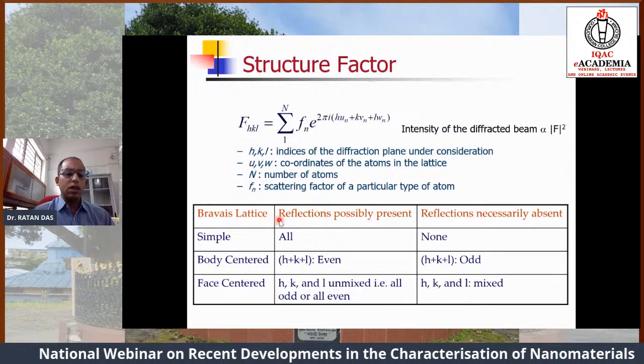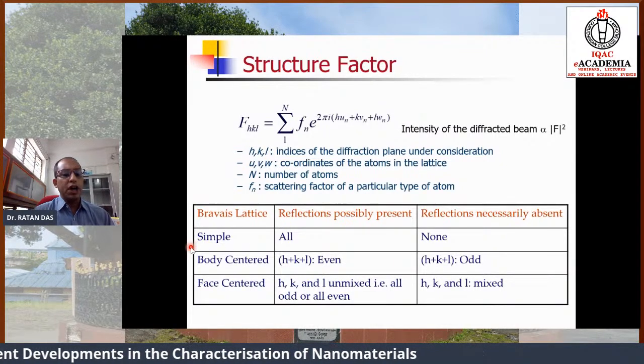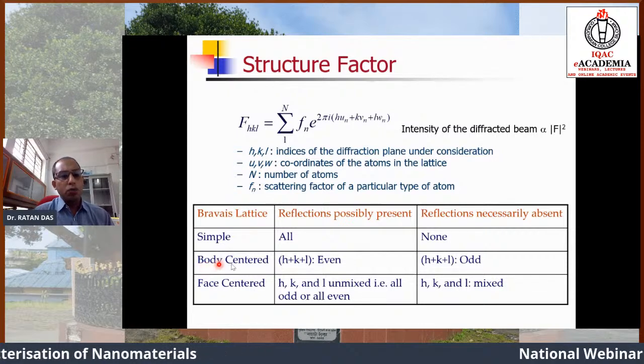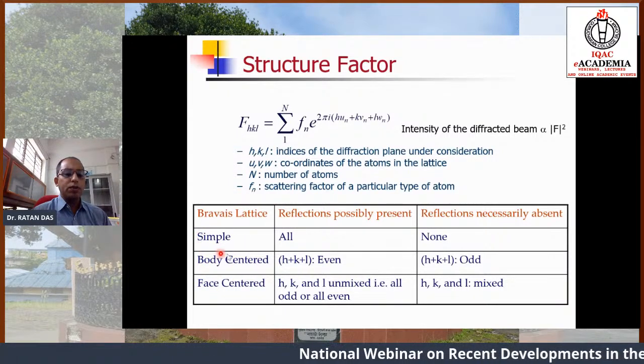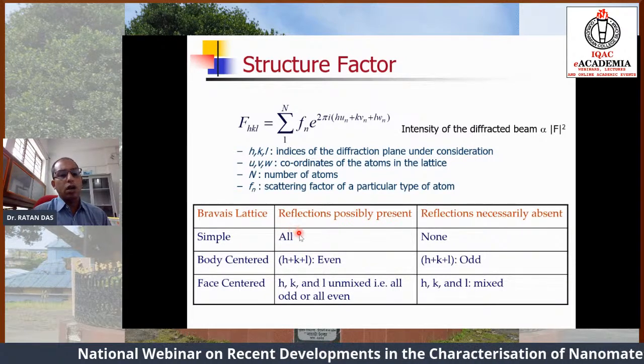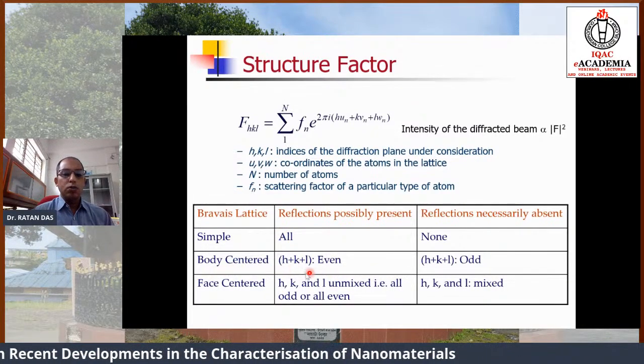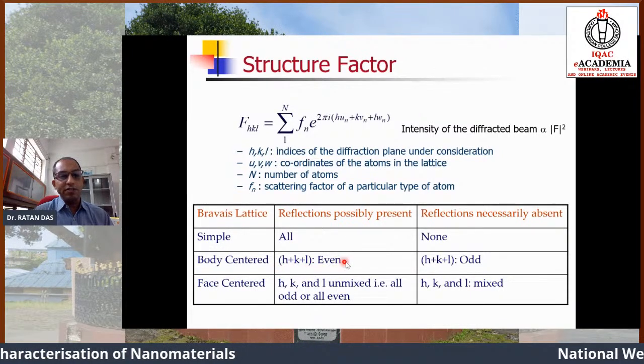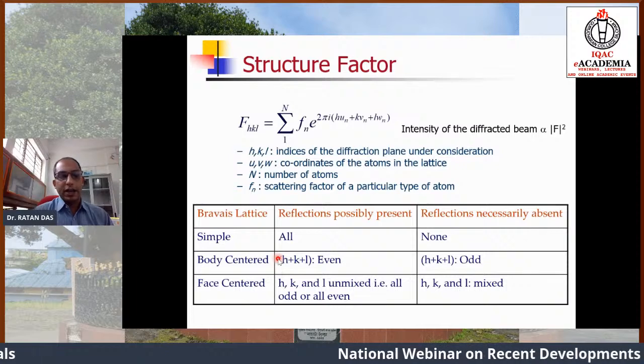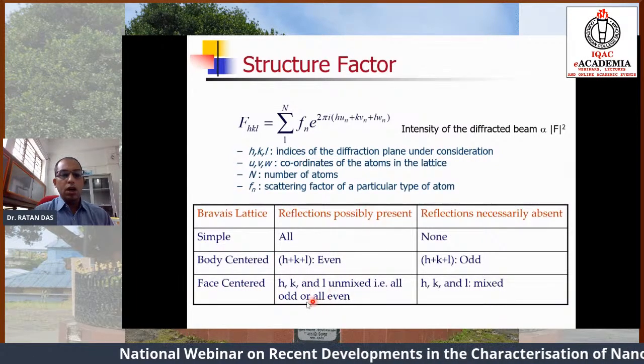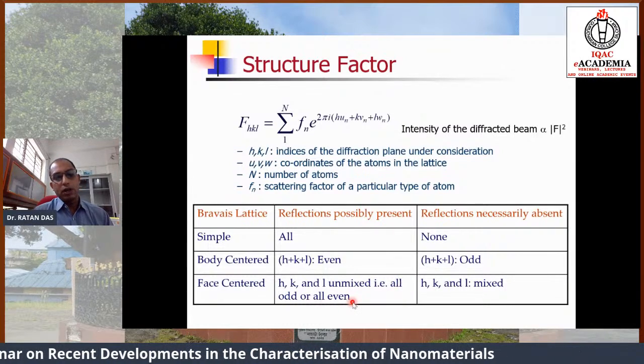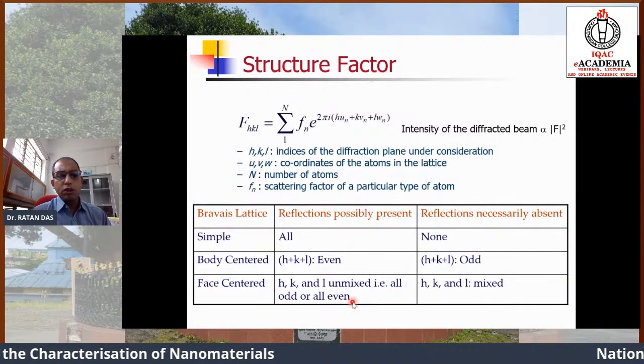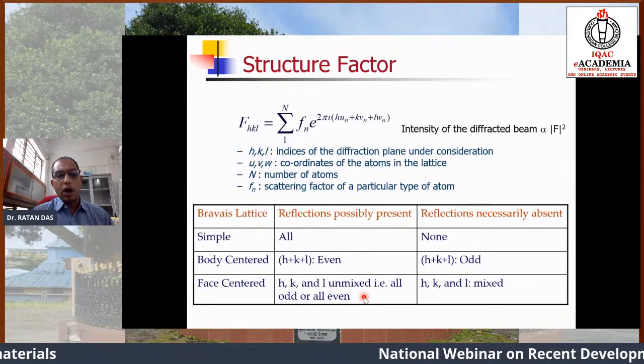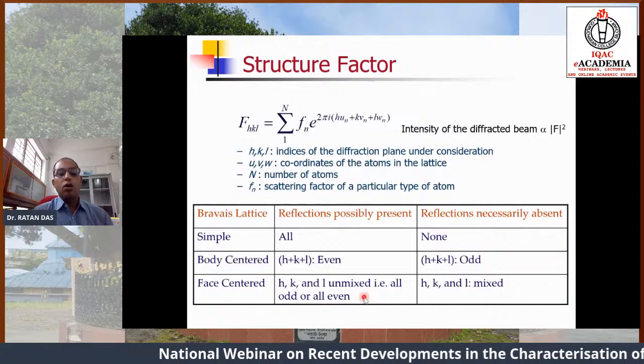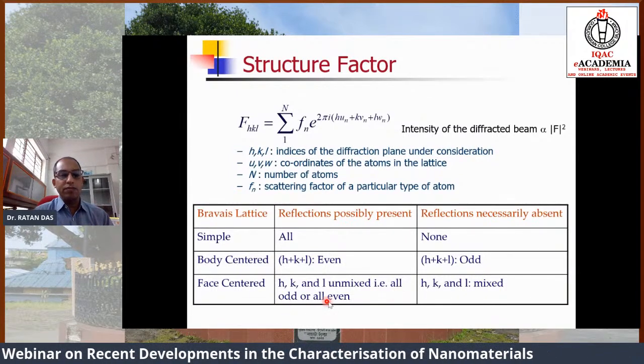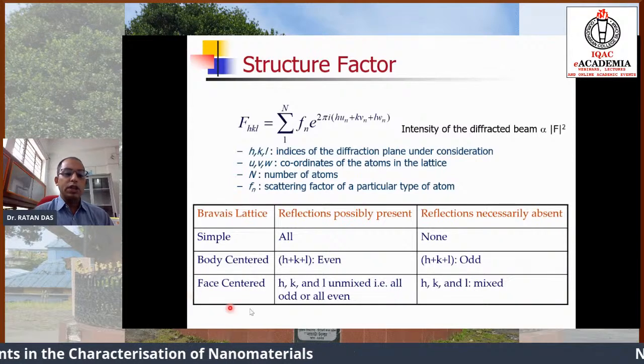But let us see that in the Bravais lattice structure we have simple cubic, body centered, or face centered structures. In the case of a simple structure all the reflections are available. But in the case of body centered, those HKL, the Miller indices, which sum to even will be available in the X-ray diffraction pattern. In the case of face centered, the HKL unmixed, all odd or all even, are available.